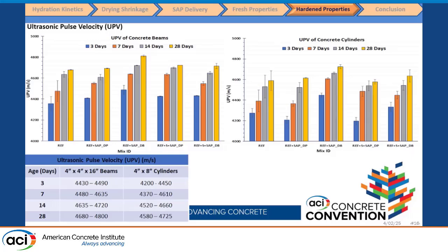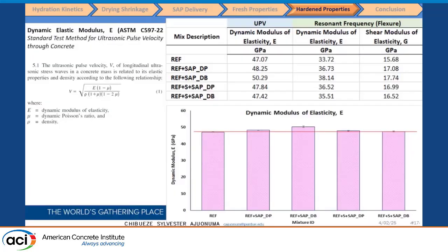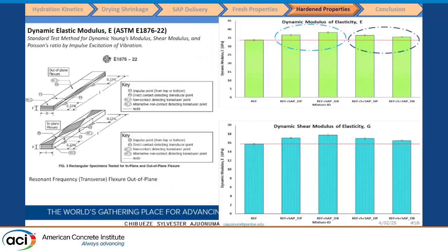It's a 3%, 4% increase at 28 days, which is also comparable with that of the direct pouring of SAP. The same trend was also observed for the 30% slag replacement. And with this, we tested the stiffness of the mix, where we tested the dynamic elastic modulus. We found that for both the dissolvable bag and direct pouring, we had close values, as you can see from the plot.